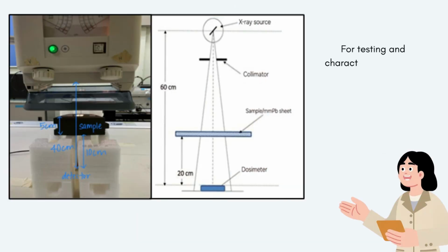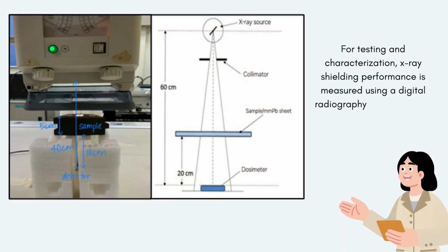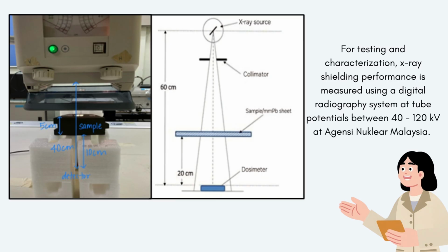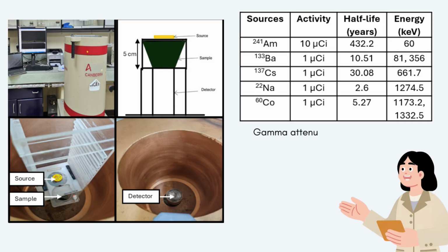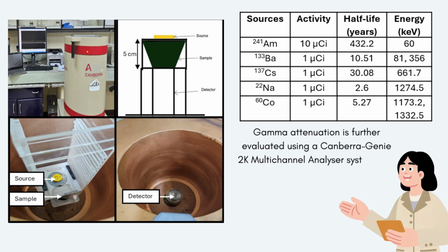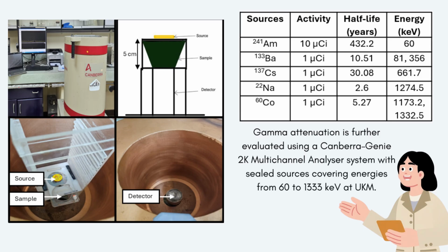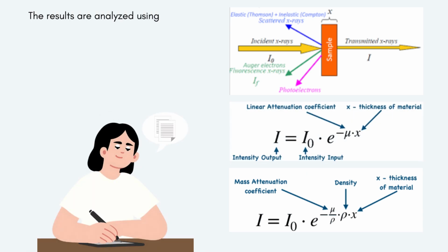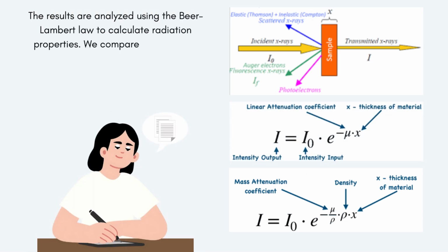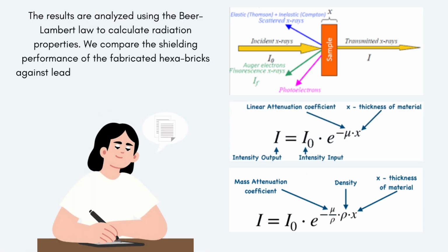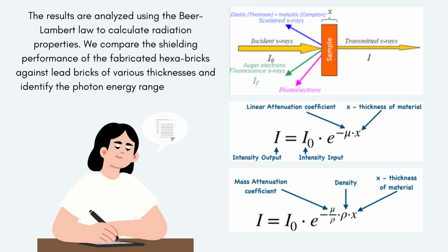For testing and characterization, X-ray shielding performance is measured using a digital radiography system at tube potentials between 40–120 kV at Agensi Nuklear Malaysia. Gamma attenuation is further evaluated using a Canberra Genie 2000 multi-channel analyzer system with sealed sources covering energies from 60 to 1333 keV at UKM. Using the Beer-Lambert law, we assess radiation properties, compare our hexabricks to lead at various thicknesses, and determine the photon range where they perform most effectively.